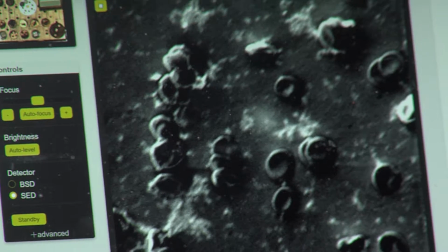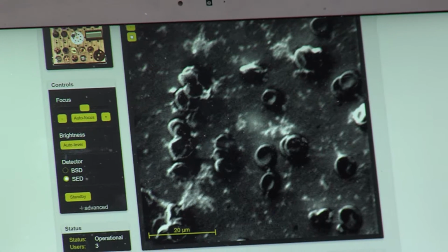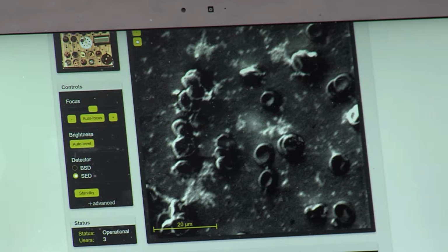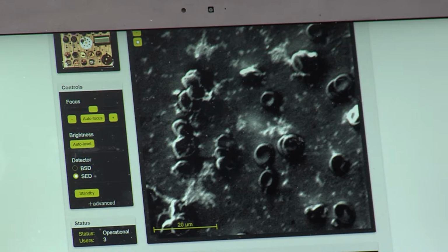They get a little bit misshapen on a scanning electron microscope. Effectively, these samples are sat in a vacuum, so you can imagine if you pull a vacuum off a sample, they can get slightly distorted. Also, unlike the chip, which is a very hard physical surface, to see anything biological we have to coat it with gold. So they've gone through a process of being put on a little piece of metal, coated with gold, then dried, put in a vacuum, and then fired at.